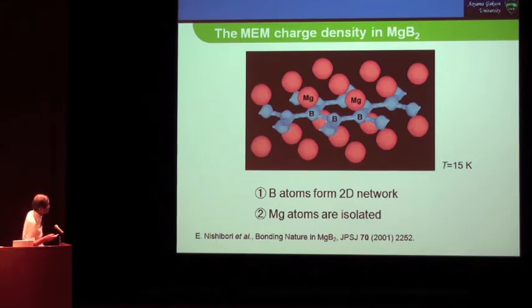If we look at these boron atoms, we can immediately understand the covalent nature of the boron and ionic nature of the magnesium. So this covalent nature is where superconducting carriers flow, so-called in the sigma bond, and also the pi bond between magnesium and boron.